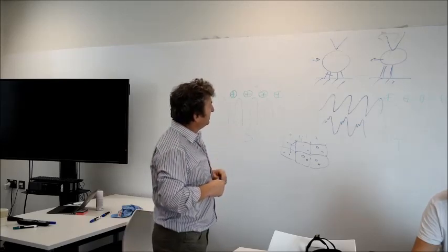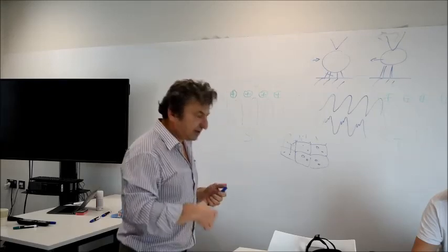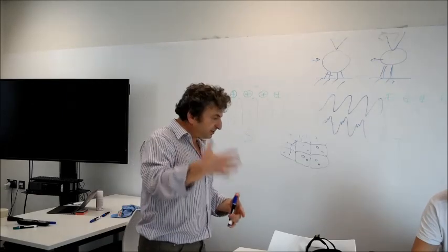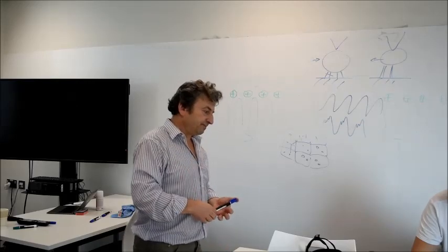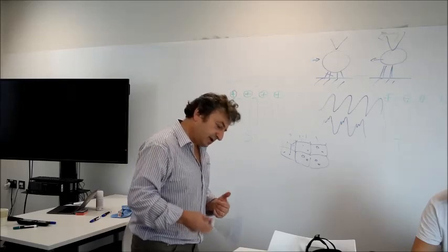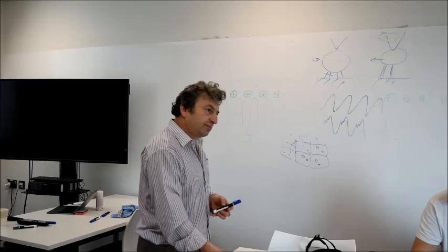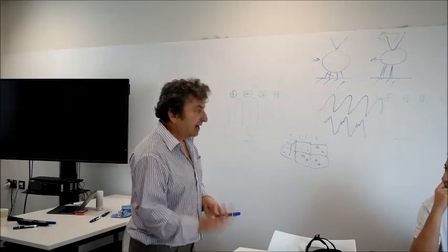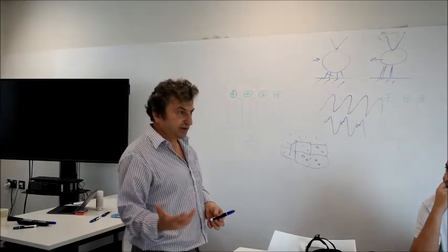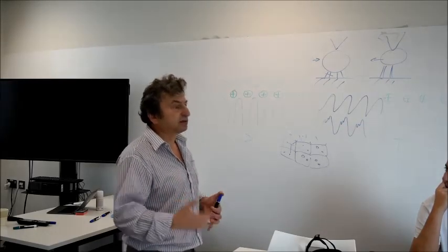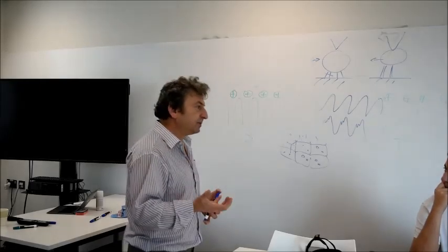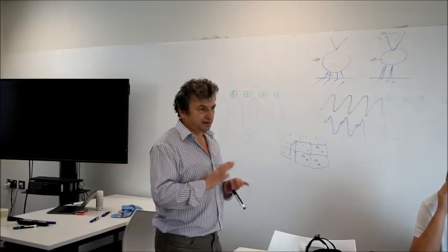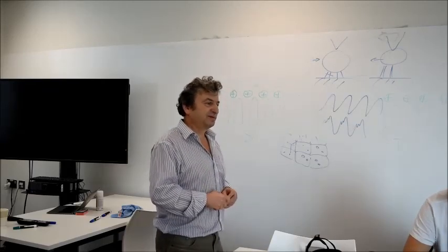Something like that we did with this copper atom, which I explained, that was a very dynamical kind of work. So, we looked at the time dependence of the manipulation itself. So how this was stochastic, because not every time. Basically the tip oscillates, AFM manipulation. This time the tip oscillated, and there is a probability of the atom jumping onto the tip, and it happens not at the very first oscillation, but it happens stochastically at the nth oscillation, and for every oscillation there's a certain probability you can assign to it at which it happens, and you can calculate nicely what is the probability of manipulating this atom. This is what we've done. So this kind of stuff, yeah. But we do different other things, completely unrelated to this. But yeah, that would take long.